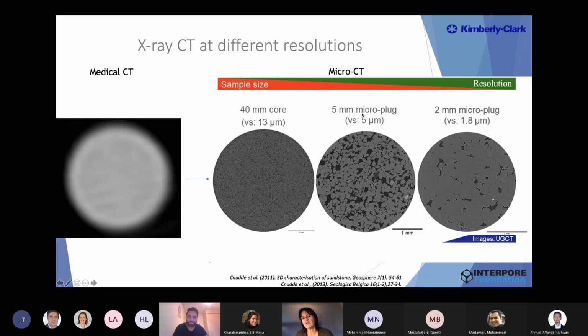The smaller the diameter of your sample is, the smaller your voxel size will be, so the higher the detail will be. It's no problem to reach resolutions or voxel sizes in the order of 1 to 2 micron in a lab on a rock sample.